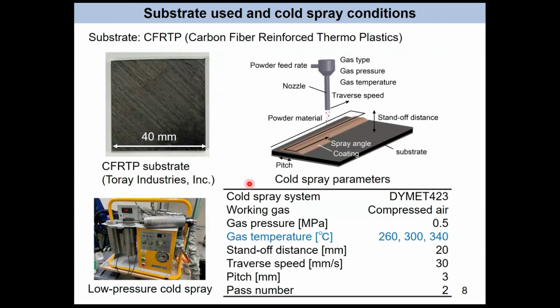And the cold spray parameters. During cold spray, we have to set many parameters like gas type, pressure, temperature, also traverse speed, and so on. But the main parameters which affect the impact velocity are particle size and particle material, and also gas pressure and temperature. So in this experiment, we change the gas temperature from 260 to 340. We choose 3 different temperatures.